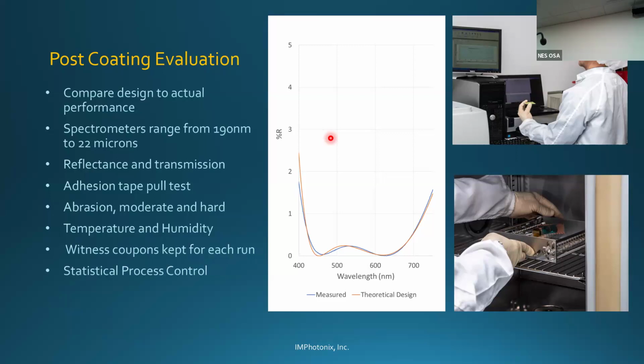And in this graph here, the actual measured one is blue, and in yellow is the theoretical design. This was our standard quarter wave, half-wave, quarter wave AR coating, standard in the industry. Everybody does this. It's called a W coat because it's shaped like a W. But we do this so often that statistical process control allows us to have very good repeatability on this.